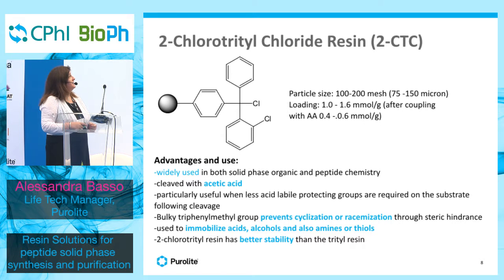The chlorotrityl resin, also called 2-CTC, has been widely used in solid phase organic synthesis and peptides. It is cleaved with acetic acid. It's particularly useful because it is a very bulky resin with the trityl functional groups, so it is very good at preventing cyclization of peptides and racemization. It is used to immobilize acids, alcohols, and also amines and thiols.